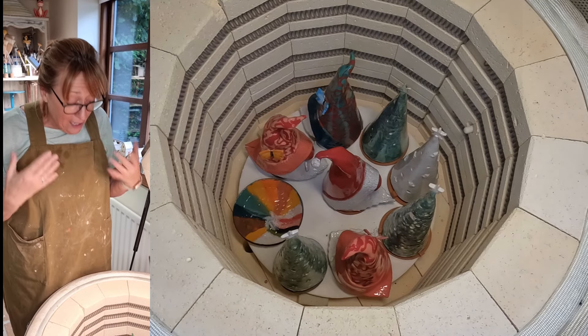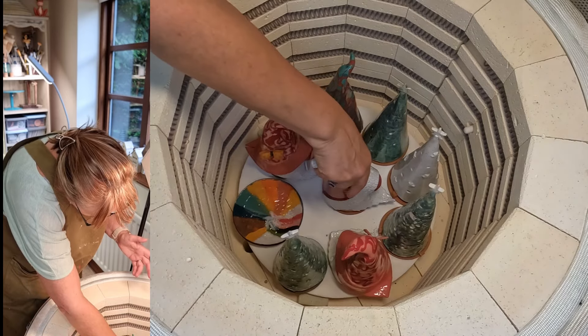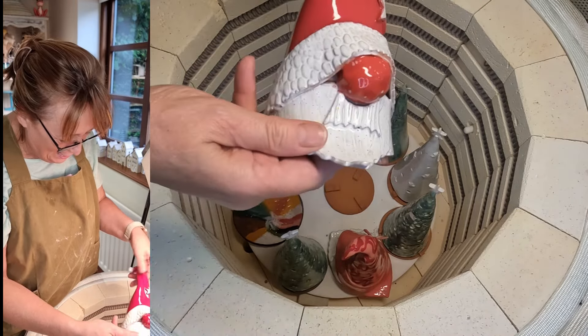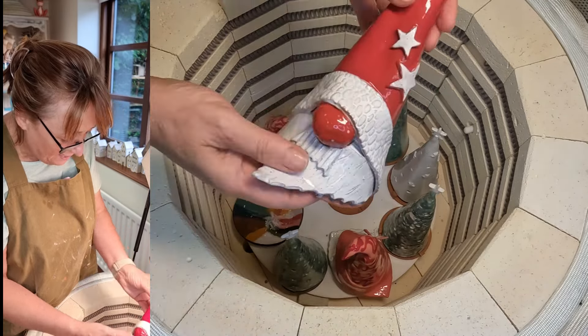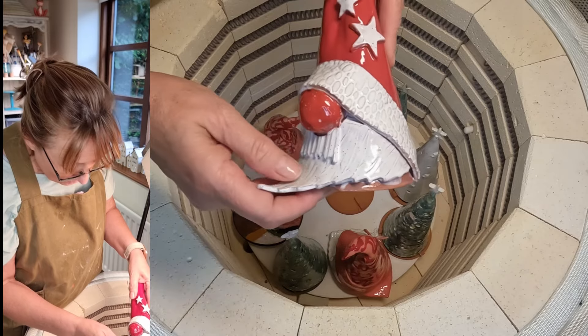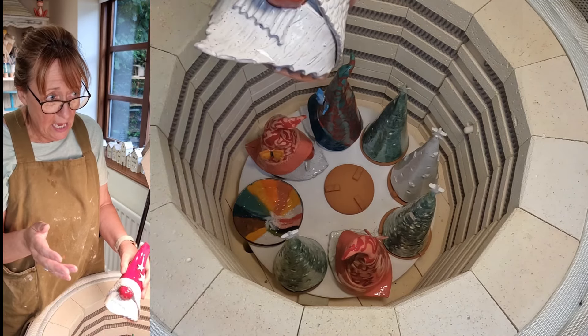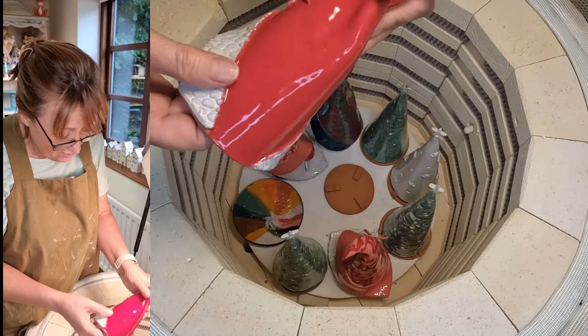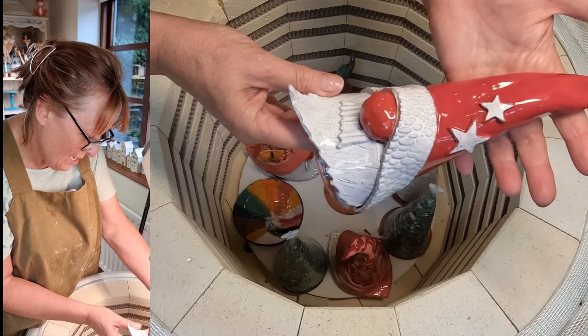Let's start - I've been doing some gnomes just playing around with some terracotta clay. This is one of the new ones. He's a Christmas gnome - look at him! Yes, I like that. The colors are much brighter when you bring it out of the kiln. The plan is I'm going to put some gold luster on here, or I might even put some gold glitter on it to give it a bit of sparkle. What happened previously was I dipped these in a white slip and did a trial on some test tiles, then glazed straight on top of the white slip and it all popped off. So this one I washed off, reglazed it very quickly, rough and ready, and it's okay. I'm pleased with that one - isn't that cute, it's about 10 inches tall.